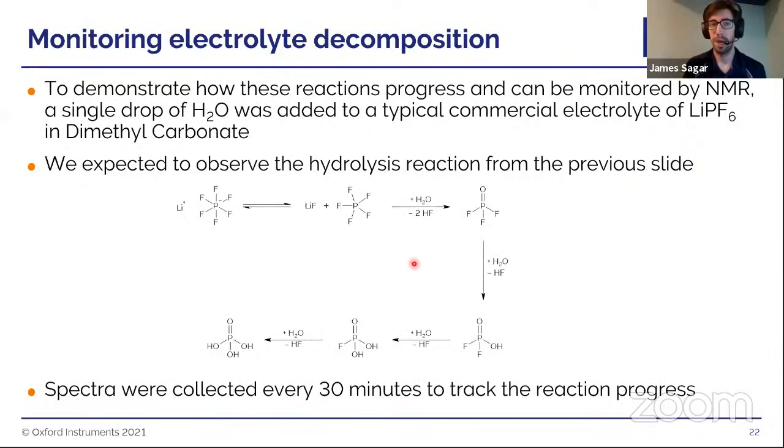So by adding a small amount of water to a commercial electrolyte of lithium hexafluorophosphate in dimethyl carbonate, we can force this hydrolysis reaction to take place. And we expect to see a degradation of this lithium hexafluorophosphate into some lithium fluoride and PF5, then a further reaction forming water and hydrofluoric acid into these phosphodifluoric acids. So we collected fluorine spectra, 19F spectra, every 30 minutes to track the reaction progress.